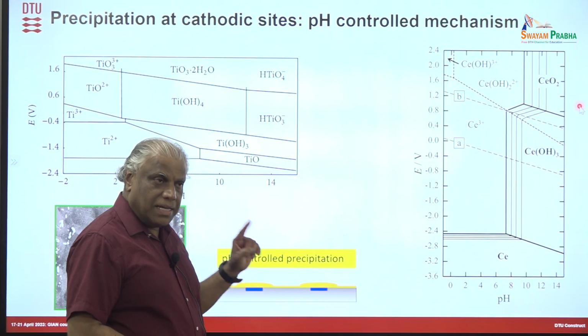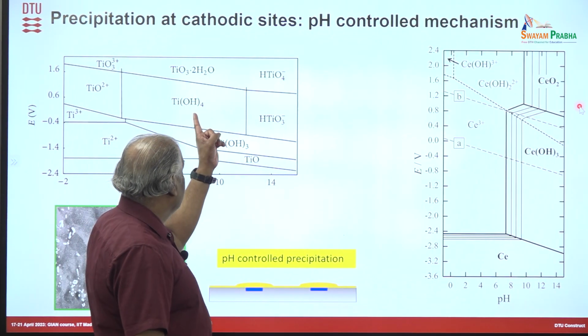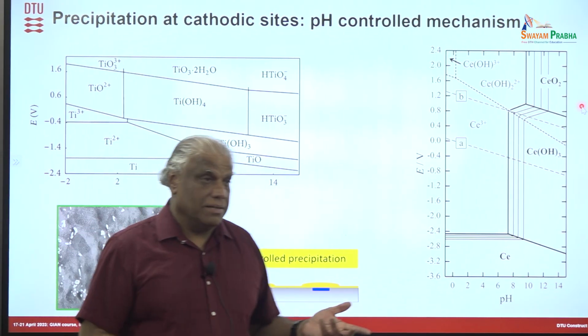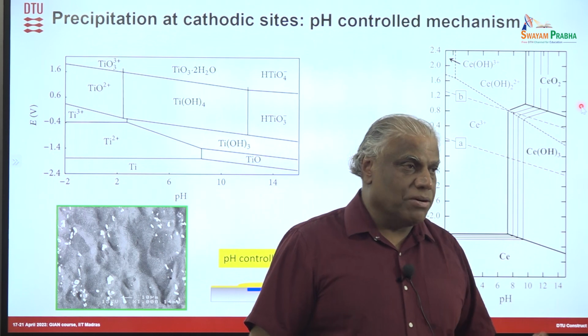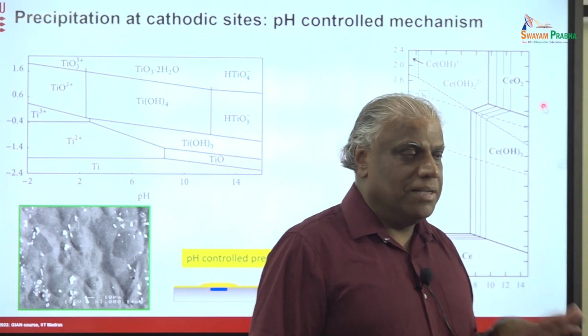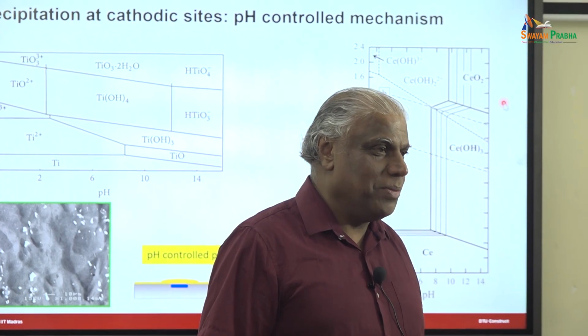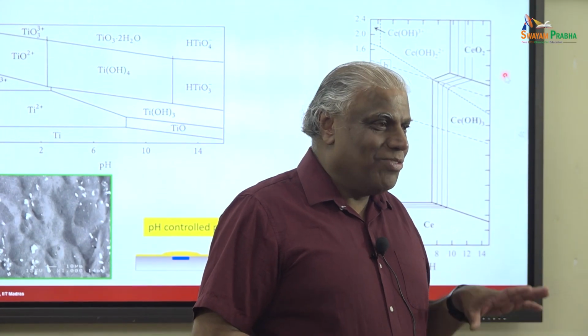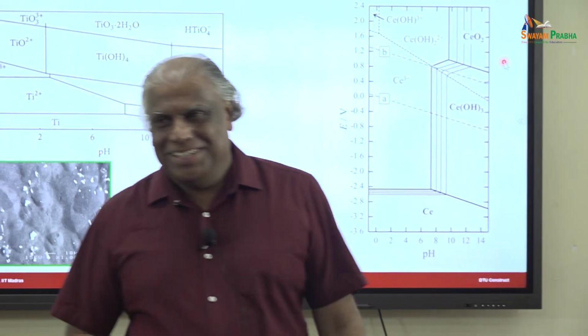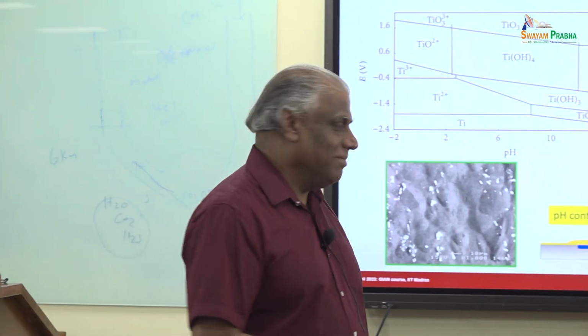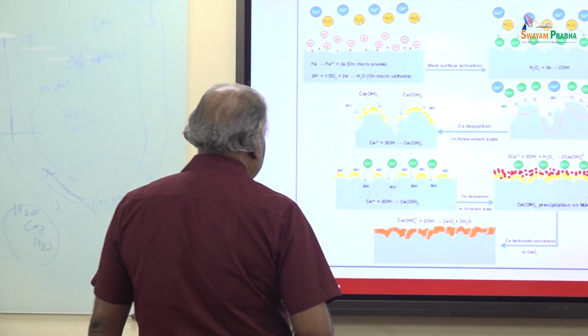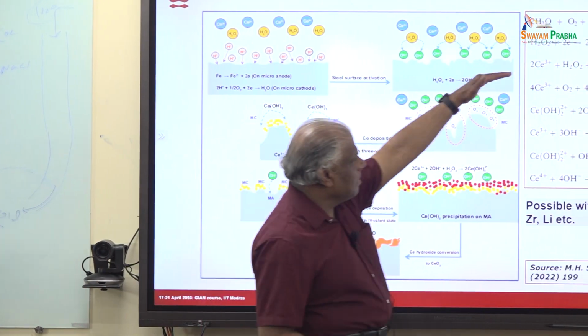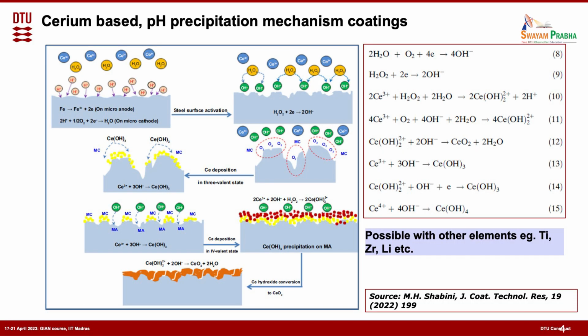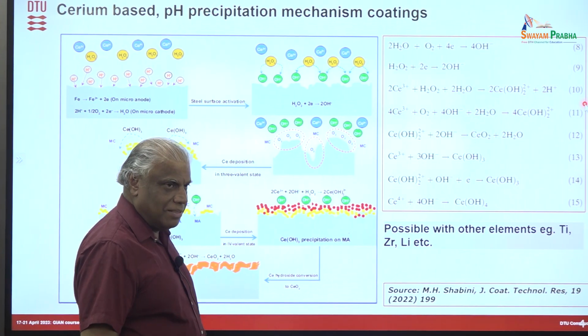Out of this, the commercial process existing today is a process using titanium and zirconium together. It's called a titanium zirconium based coating. That's the only one that is commercial today. People are using it as a replacement for chromium. Ask the question, is it as good as chromium? No. It is still much worse than chromium, but that is the alternative. This slide just shows the mechanism of this coating formation, the different steps in the reactions: the pH changes locally, and then the cerium hydroxide precipitates, and that is a sequence. It's just showing the sequence, otherwise there is not much in this.